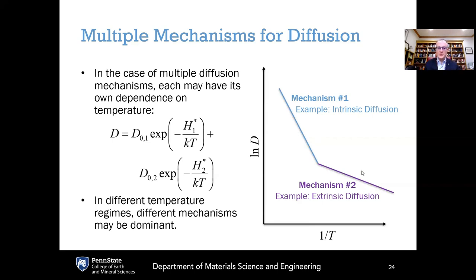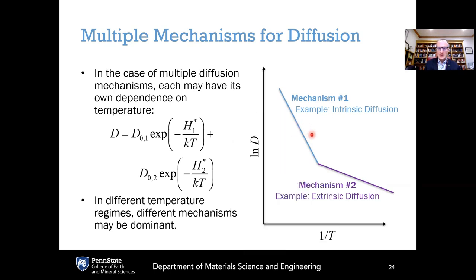and lower temperatures on the right-hand side. And in that case, there are two different regimes here where we've got two different mechanisms activated. They have two different activation barriers, a steeper one here at the higher temperature end and a shallower one at the low temperature end. And we can capture that by a summation of two different Arrhenius terms shown here.